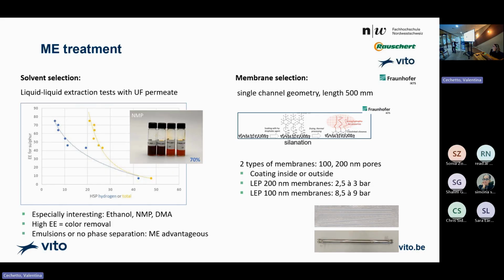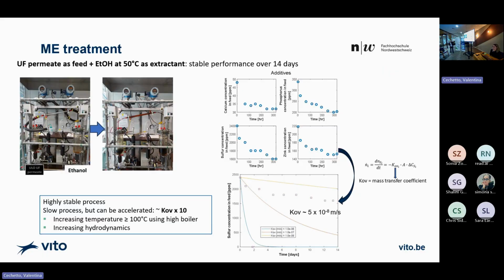So using a membrane in the extraction process is really very positive. So as to membranes, we rely on the nicely silanated membranes of Fraunhofer and Rauschert, and we typically take 100 to 200 nanometer membranes with a very hydrophobic surface. We have an experienced partner from Basel, Switzerland in this project, and they have a nice lab setup, and it's a huge amount of tests here, and you see the good removal of different metals.